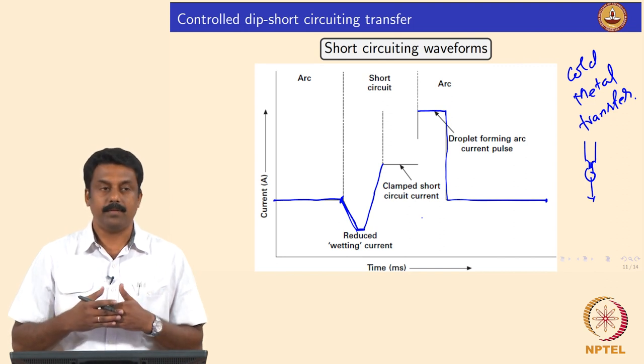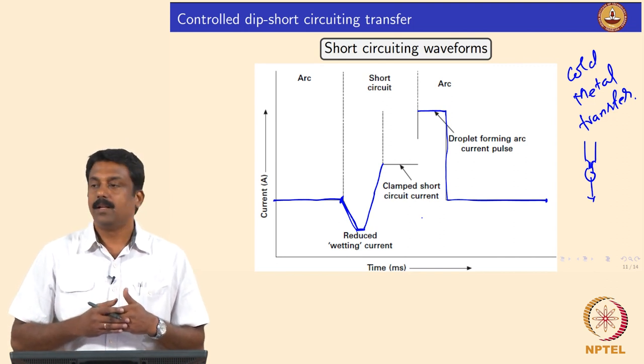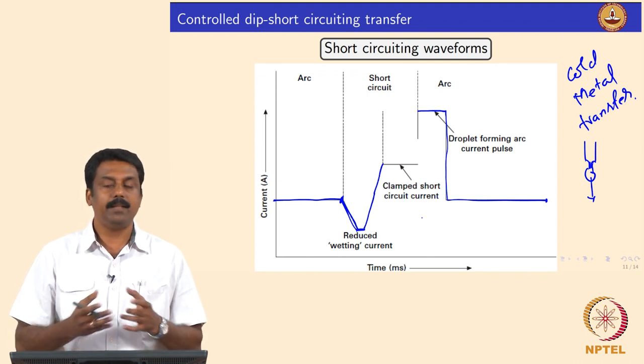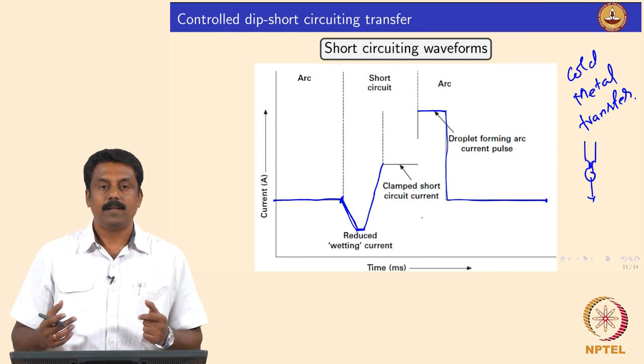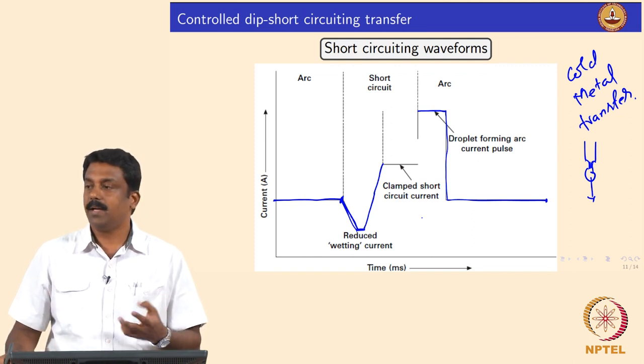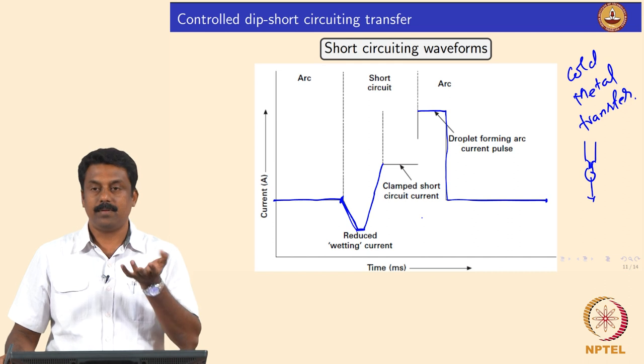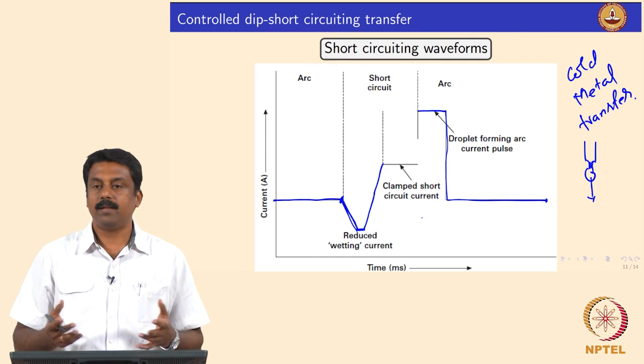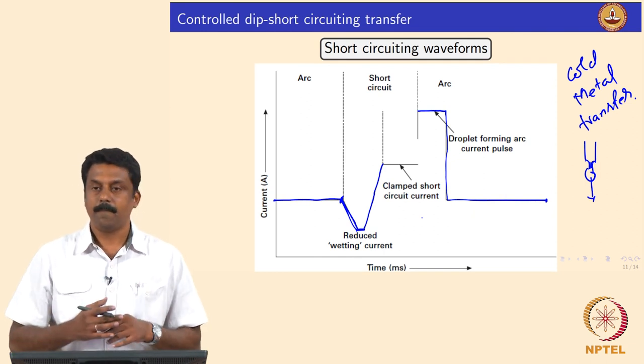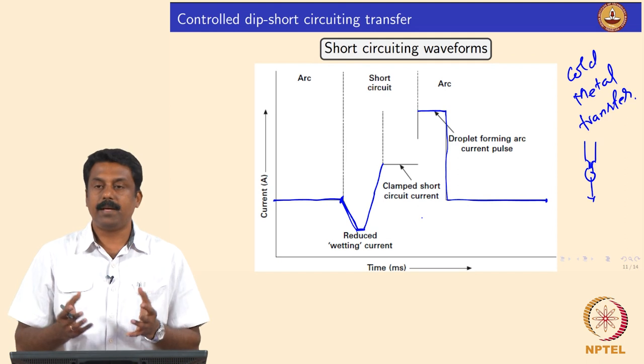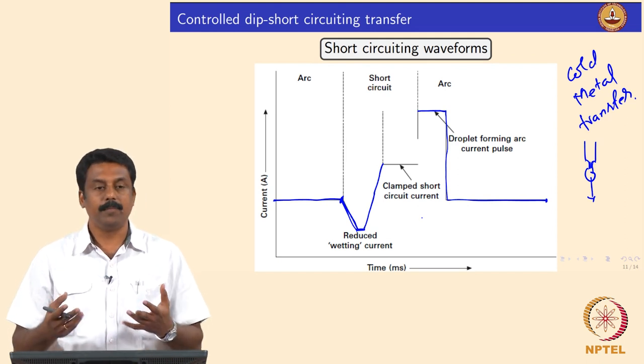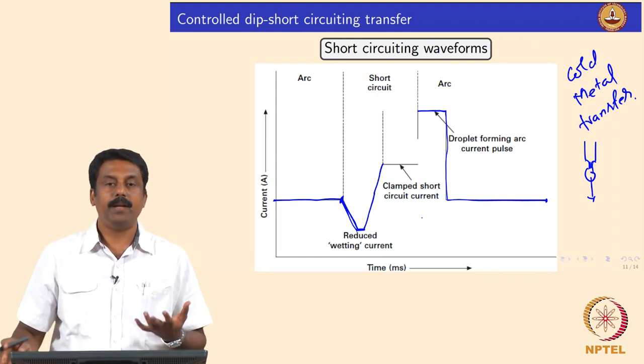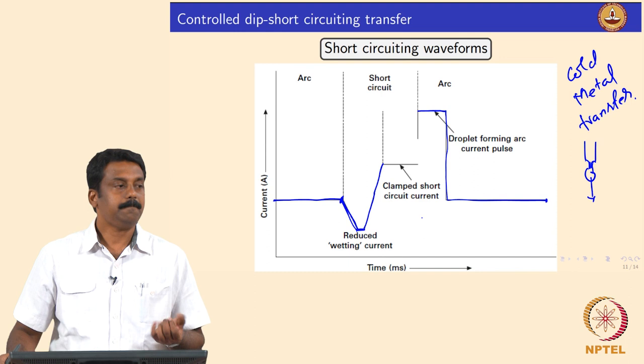For example, if you want to avoid intermetallic formation in dissimilar welding, you have to minimize the heat and make sure the weld pool temperature is not heated up excessively — otherwise diffusion of alloying elements may cause intermetallic formation, for example in iron-aluminium welding. In those kinds of applications this process is extremely suitable because the heat in the weld pool is minimized, which is the way we avoid all these detrimental metallurgical reactions.